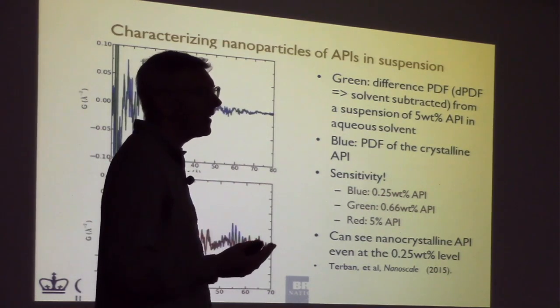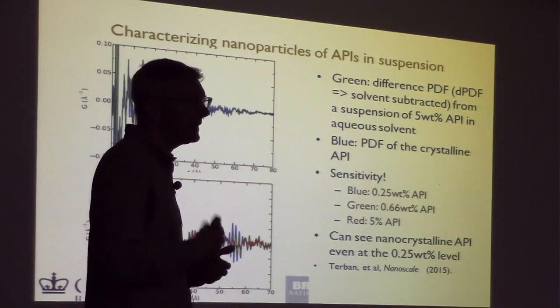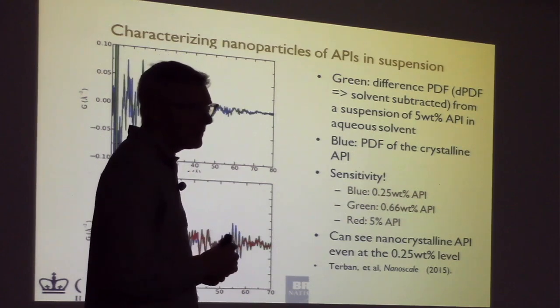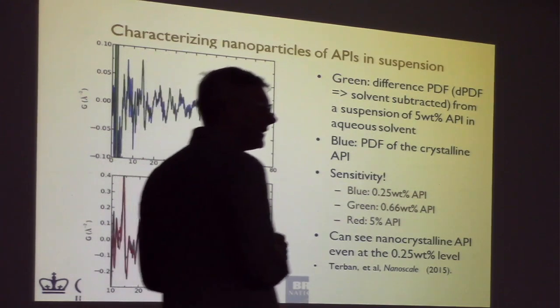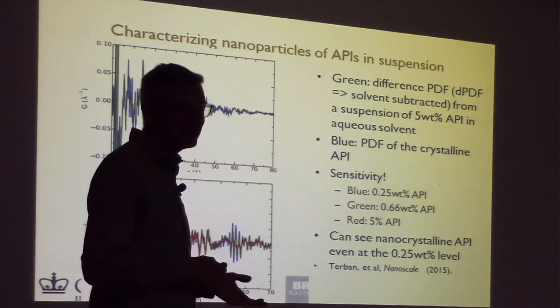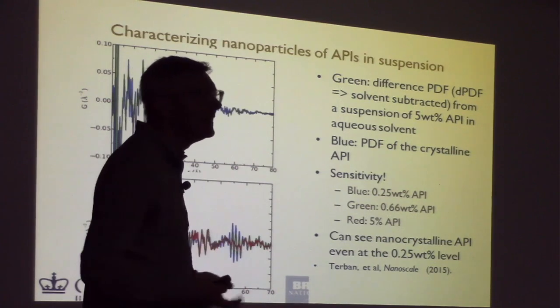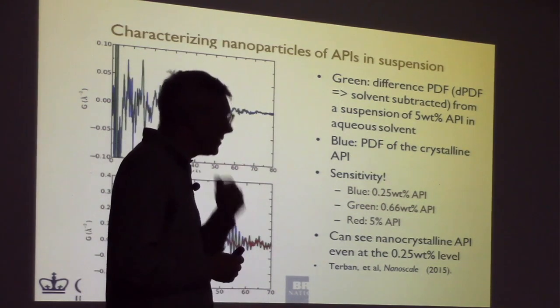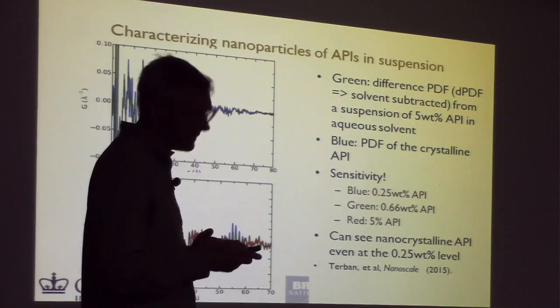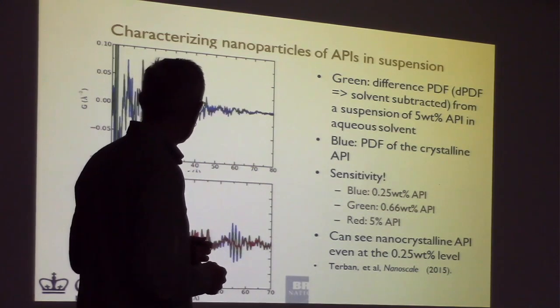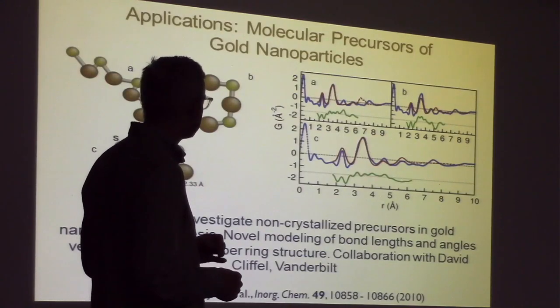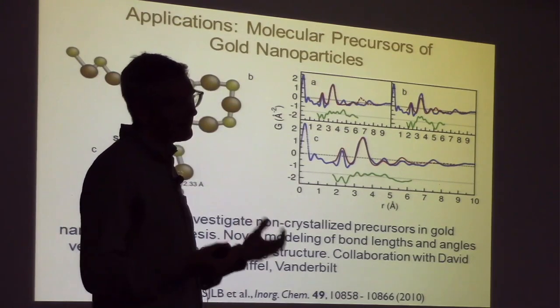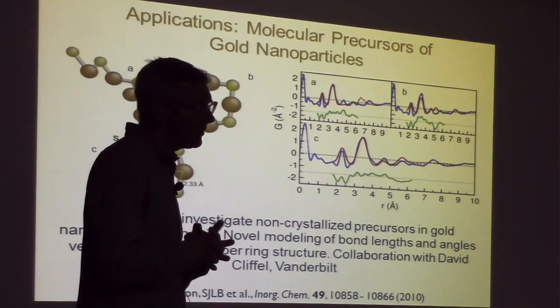So an organic is made of carbon. It's a low atomic number, weakly scattering material. So we were basically astounded. I didn't believe this result, but I couldn't not believe it because it's true. So we're now able to look with very high sensitivity, as well as looking at small size things. And that allows us to do very interesting things, because we can look at precursors.